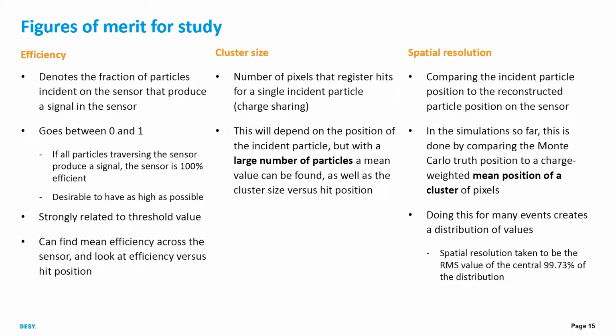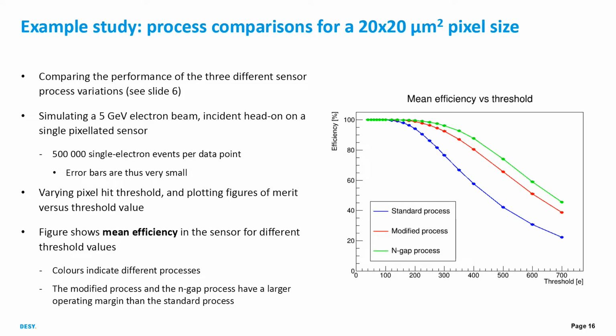Now, the cluster size is the number of pixels that register a hit for a single incident particle. So it's basically a measure of charge sharing. And this will, of course, depend on where the particle hits, whether it hits between pixels or in the center. But if we do a large number of incident particles across the whole sensor, we can find a mean value. The spatial resolution we get from comparing incident particle position to reconstructed particle position. So far in the simulations, we've taken the Monte Carlo truth as the incident particle position, and the charge-weighted mean position of a cluster of pixels as the reconstructed position. And again, doing this for many events, we can get a distribution of values, and from this extract the sensor resolution. So here's an example study comparing the three processes, standard, modified, and NGAP, for a 20 by 20 square micrometer pixel size.